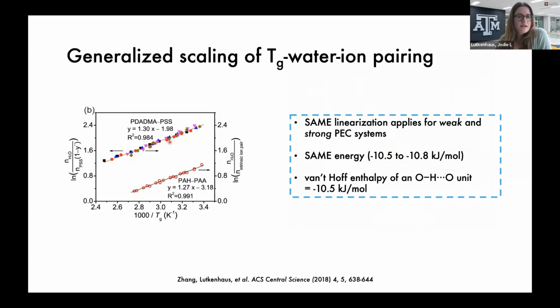And these are the two systems that we plot in the linear form I showed you. So these two different systems, PDADMA PSS, the strong polyelectrolytes, and PAH PAA, the weak polyelectrolytes, both follow the same linearization. And you can see with just your eyes, they have about the same slope. They have different y-intercepts though, but they both have about the same slope, which gives you about the same energy. So this is pointing to the idea that maybe the way polyelectrolytes relax and go through the glass transition in polyelectrolyte complexes, maybe it's a more general phenomenon regardless of the polyelectrolytes you choose. Maybe it has to do with somehow that intrinsic ion pair has to be released momentarily with water mediating that release so that the polyelectrolytes can slide against one another.